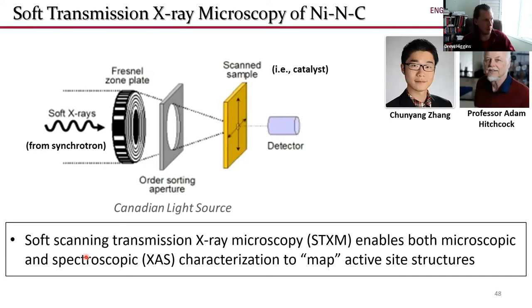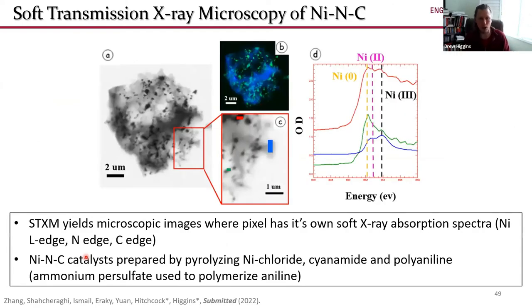So right when I started at McMaster, I coerced Adam Hitchcock out of retirement because he truly is one of the world leading experts in a technique called soft transmission X-ray microscopy. So a technique that I'll call STXM because that's just a mouthful. STXM means soft transmission X-ray microscopy. We have a co-advised student, Chunyang Zhang, who's been leading a lot of these efforts on using STXM to understand these nickel nitrogen carbon catalysts. So essentially what STXM does is it provides a microscopic image of a catalyst particle, something that you might expect from a transmission electron microscope, for example. But every single pixel on this image is a correlated X-ray absorption spectrum that gives us information into the chemical structure that is present at each one of those pixels.